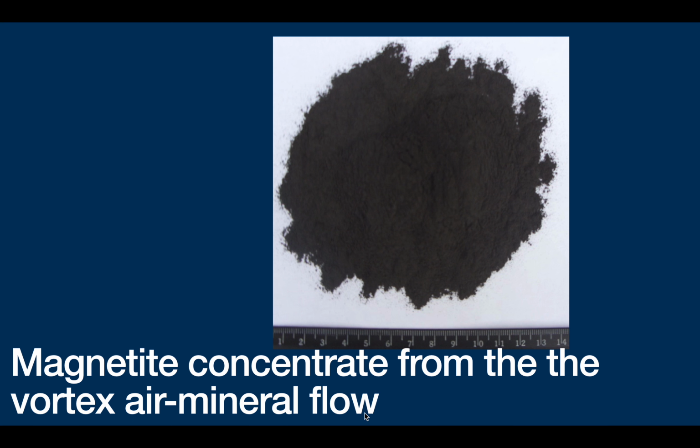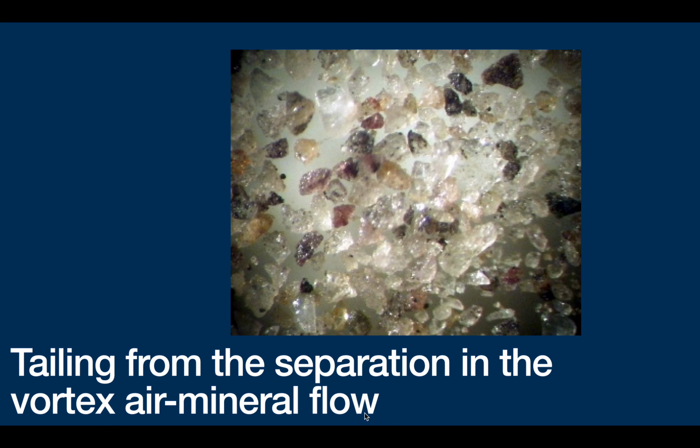A more detailed description you can find in our full paper. I will just say that at the end of the technological process we receive a concentrate that corresponds to the composition of iron ore concentrate of medium quality produced by mining and processing plants. The main benefit of the proposed technology is reagent-free enrichment of iron ore. There is no need for any additional reagents or toxic or hazardous agents. Tailing from the separation in the vortex air mineral flow is quartz sand and could be used in the building industry.